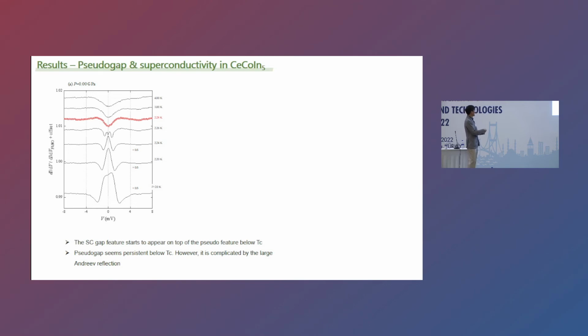And this is the data near the TC. So these are the dips, right? And the TC is around 2.25 Kelvin. Then with slight suppression, from 2.25 to 2.36 Kelvin, you see enhancement near zero bias. The enhancement at zero bias is due to Andreev reflection due to the spectral gap. That's what you see: the dip switches to Andreev reflection.